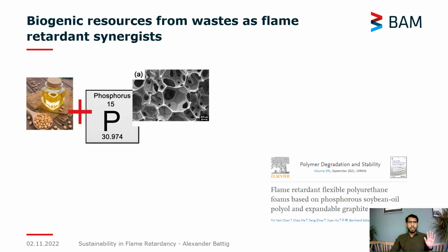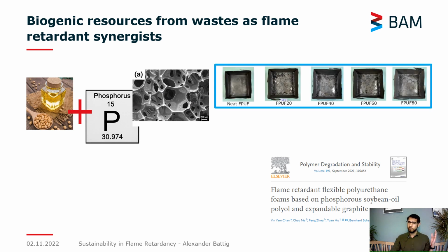So it's not just epoxy resins that we investigate, but we also did research on foam structures, particularly using phosphorylated soybean oil and expandable graphite in flexible polyurethane foams. And what I'm showing you here is a pure flexible polyurethane foam with different increasing amounts of phosphorylated soybean oil. Now, the soybean oil was used as a functional diol in flexible polyurethane foam. So that means it was used as a building block inside the material, and it didn't have the strong effect that we really were looking for.